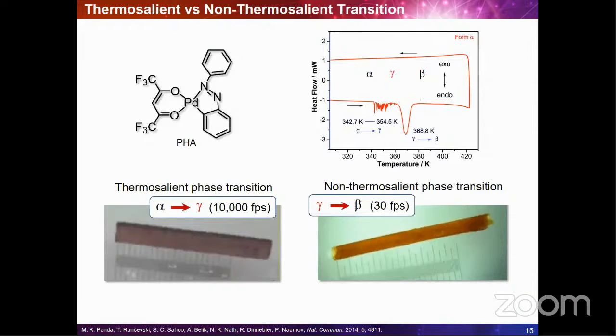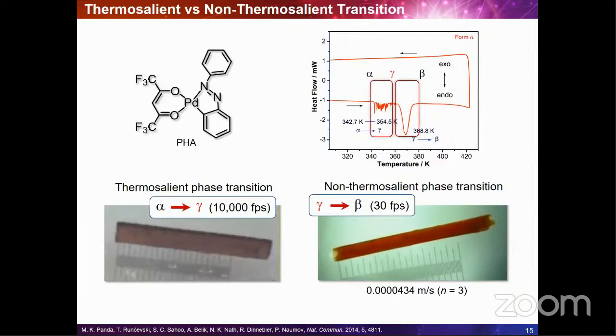So they are very, very fast. In fact, the thermosalient crystals are among the fastest switching materials reported to date because there is a concerted structural change associated with the martensitic phase transition, and this occurs 4 to 5 orders of magnitude faster than some other non-cooperative transitions in the same or other materials. For example, in this case, we have 2 phase transitions, one thermosalient, the other one is not, and they're only about 10 Kelvin apart, and the propagation rate in the thermosalient phase transition is 5 orders of magnitude faster than that of the second non-thermosalient phase transition.